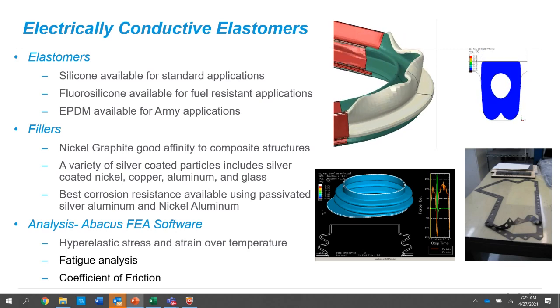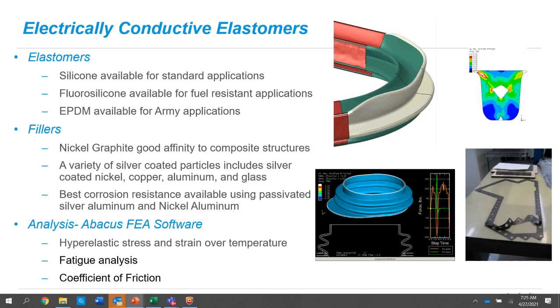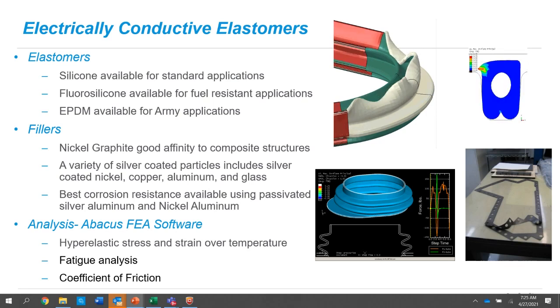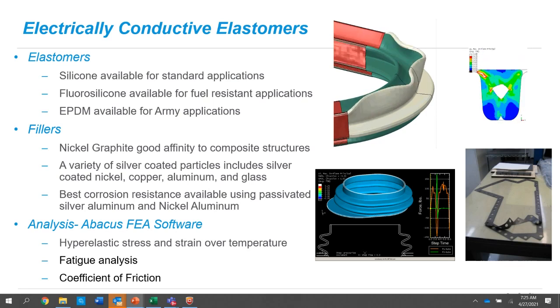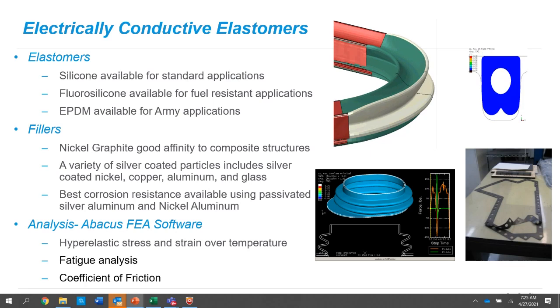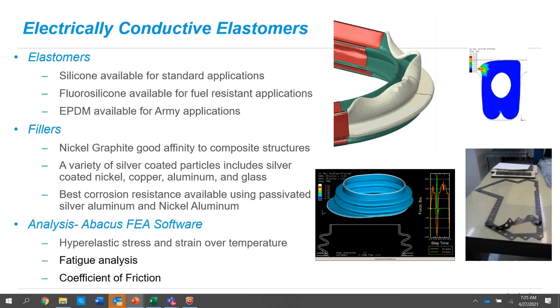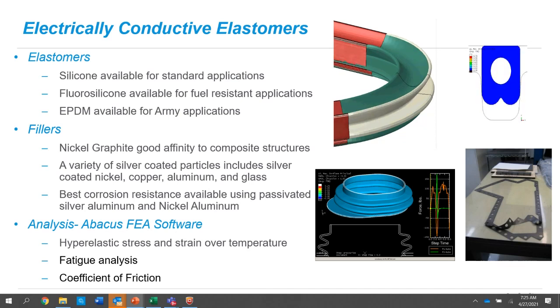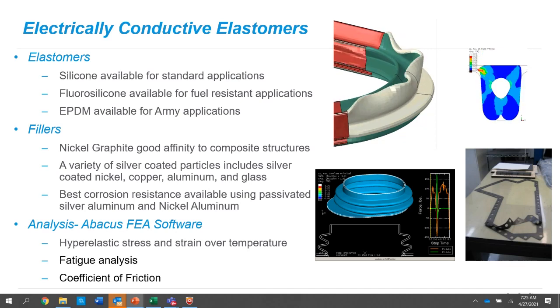We use a lot of that, and it's very good in composite applications. So if you're going against a graphite structure as a gasket, then the nickel graphite is very good, has a good affinity to that, very little corrosion. And then, like I said before, the other fillers are usually silver coated because of its really good conductivity, but then you'll use a base material, one, to reduce cost, and two, for better galvanic compatibility.